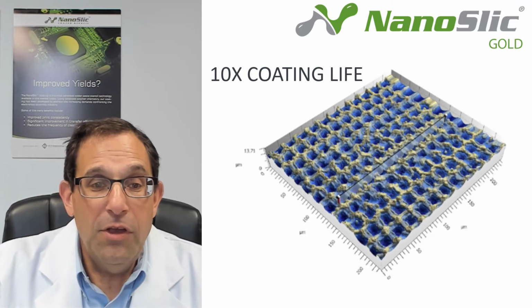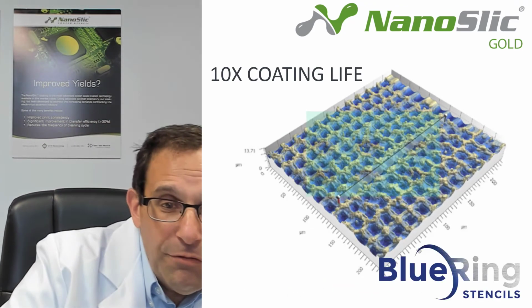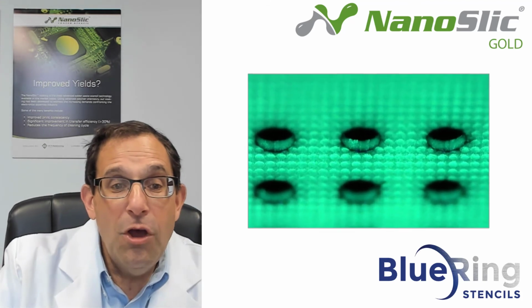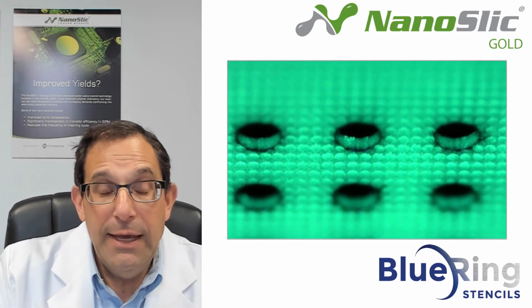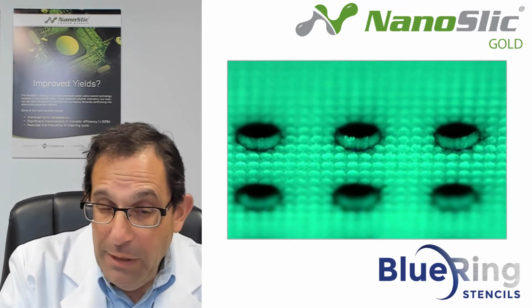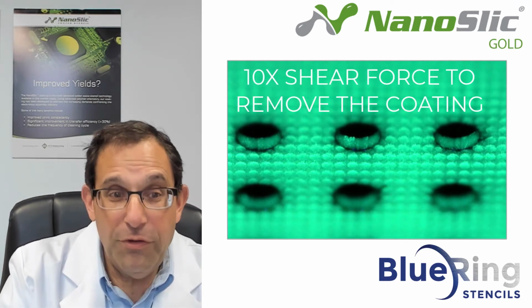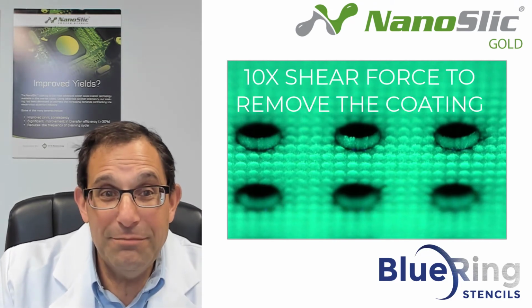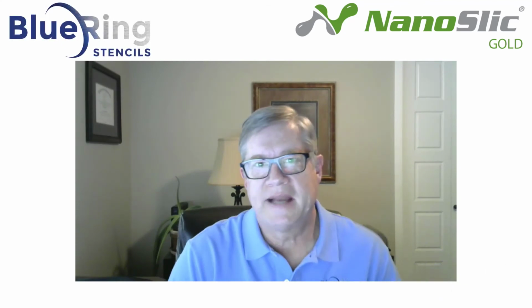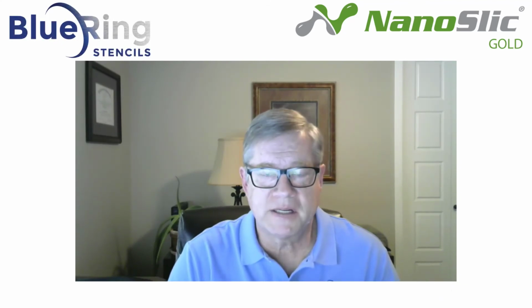This new process increases the surface area of the foil around the apertures over 50%, and it takes now approximately 10 times the shear force to remove the coating from the stencil. So let's look at the data supporting this huge improvement in our NanoSlic Gold technology.